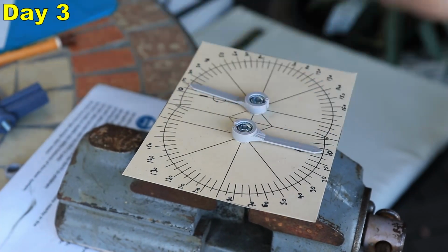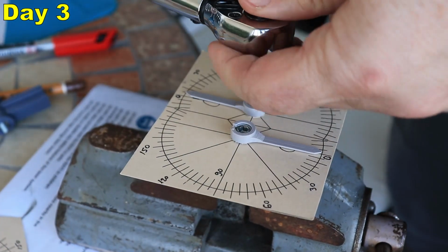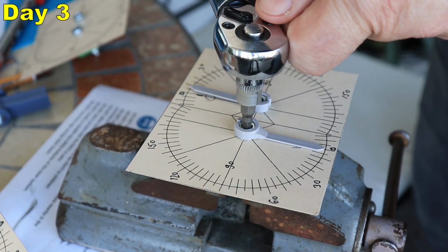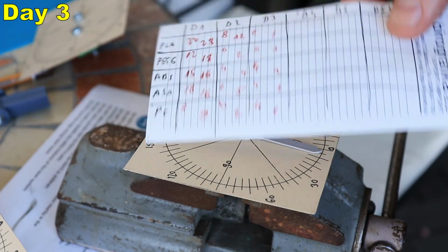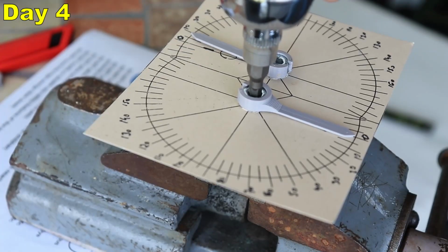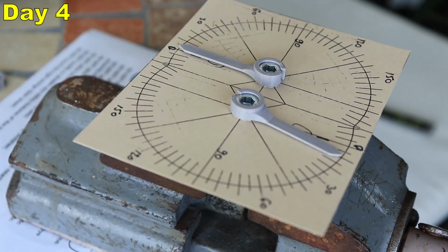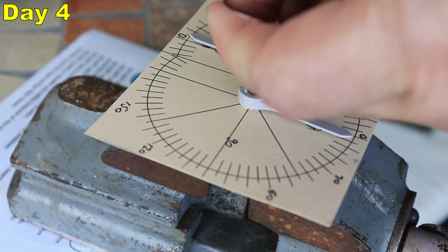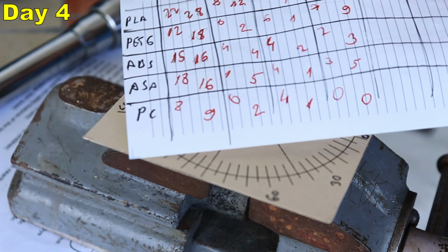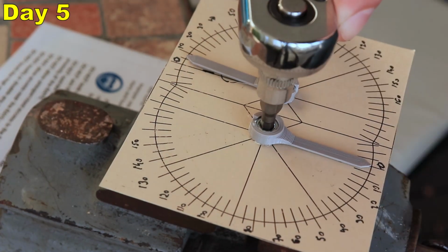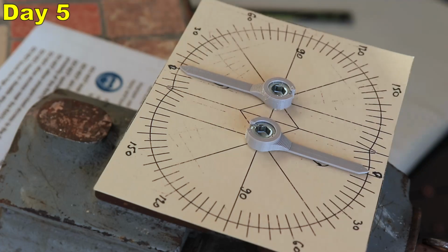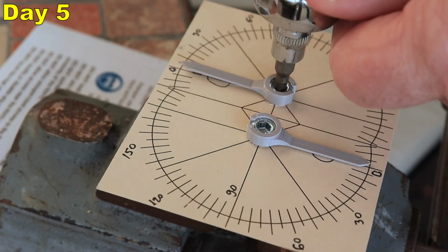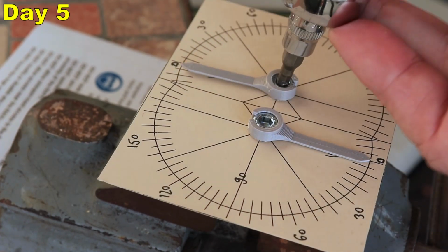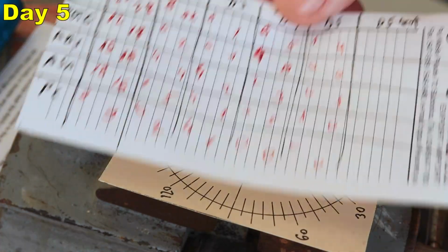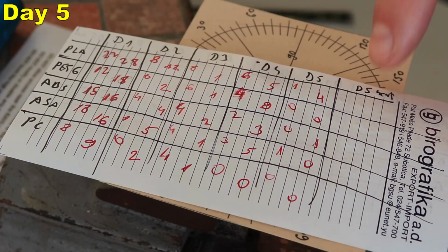PLA, PETG, ABS, ASA, polycarbonate. End of day 3. PLA, PETG, ABS, ASA, polycarbonate. And this is the state after day 4, absolutely no movement of the polycarbonate. PLA, PETG, ABS, ASA, polycarbonate. And this is the state after day 5, and now it goes to the heated enclosure for 1 hour.